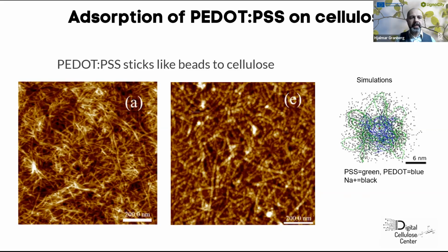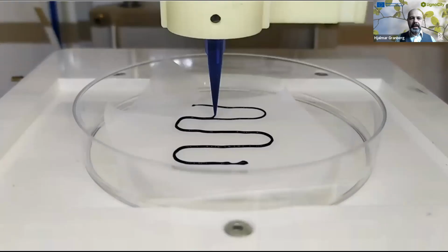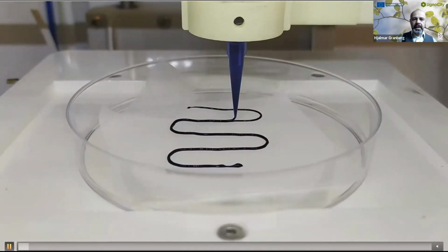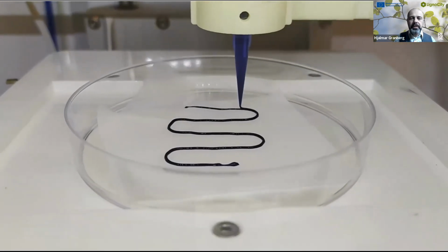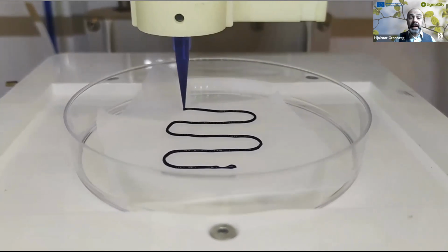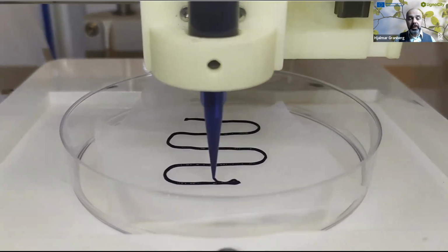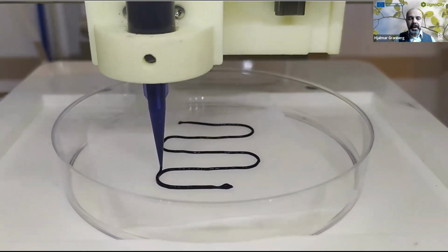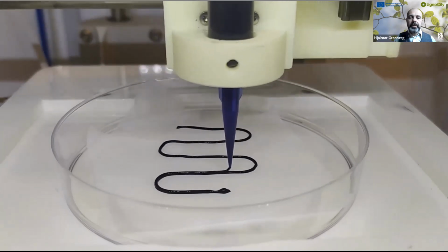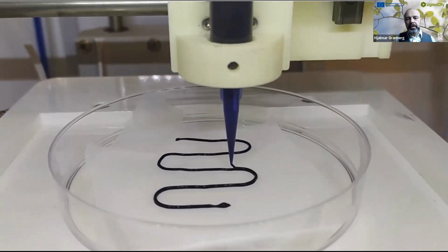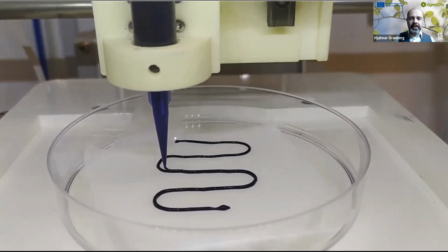We have also compared this to simulations and we got really good results, which can predict what's happening in a more complex environment. And we combined all this into a design where we actually can 3D print cellulose together with a conducting polymer. And here you can end up with both electronically conducting and ionically conducting material.